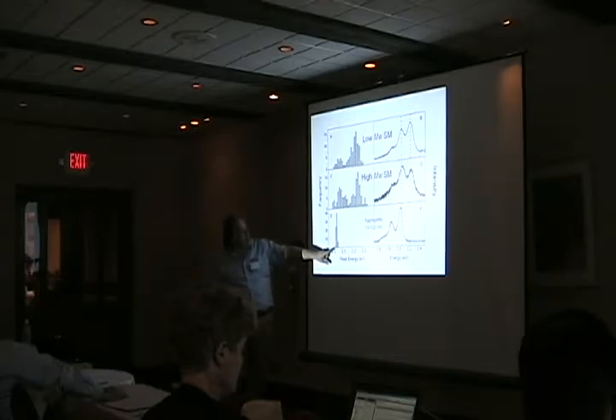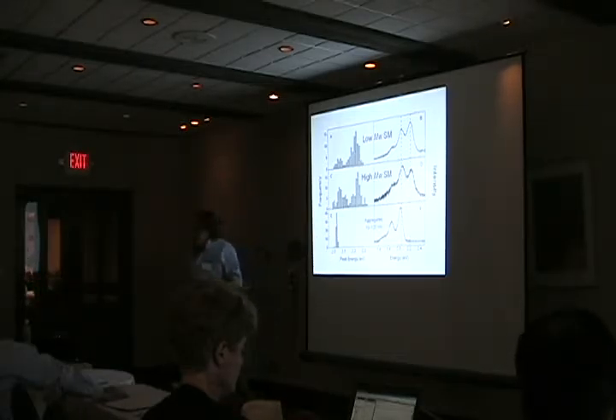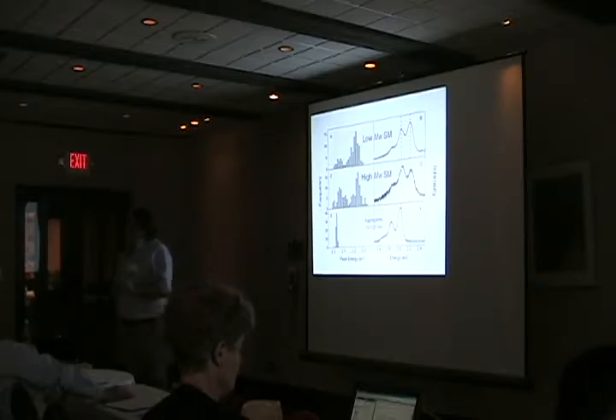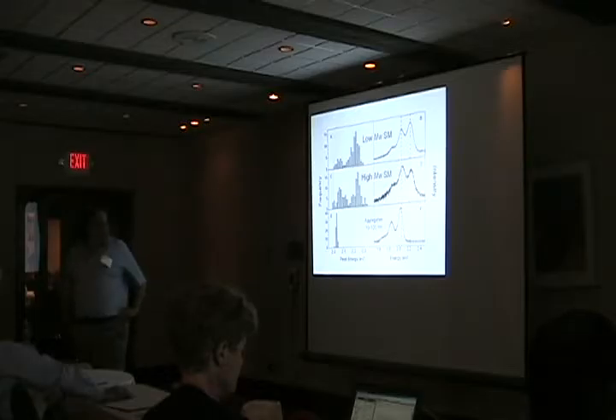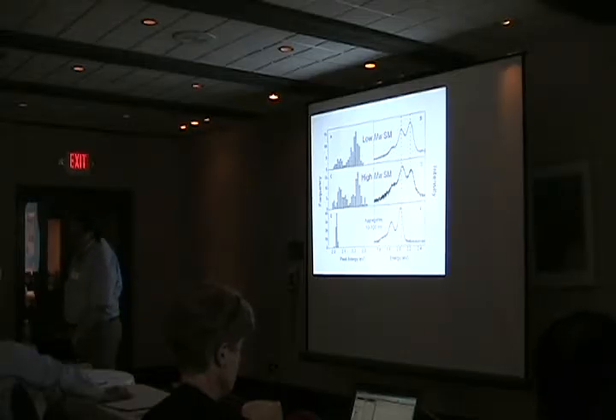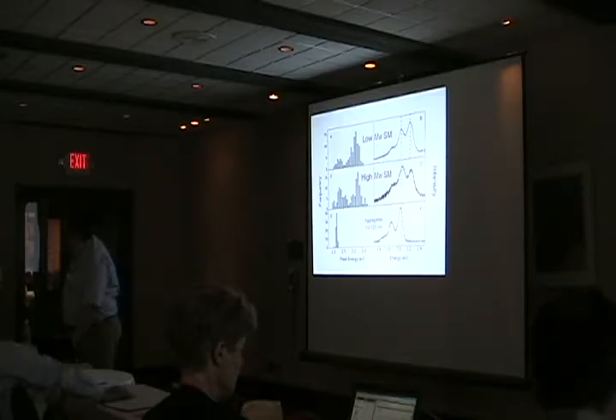And this amazing effect where you move into aggregates and the spectrum both shifts red a little bit and the histogram narrows tremendously is the bulk limit. And the size distance where that occurs is about 15 nanometers. And what there appears to be is a cooperative folding of the system when it gets large enough to really start producing a lot of these red sites.